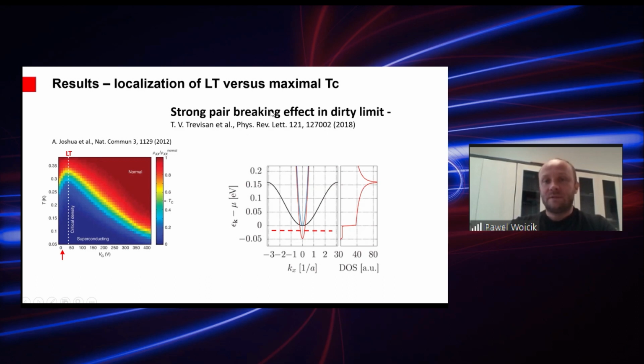So this theory says that it is possible, of course, to obtain this characteristic shape, because, for example, if the chemical potential is located somewhere here, okay, so we are at this graph, we are here, so the superconductivity is induced in the lower lying band here. This is the band dxy, and we have superconductivity. Then, if the chemical potential increases, we have a Lifshitz transition.